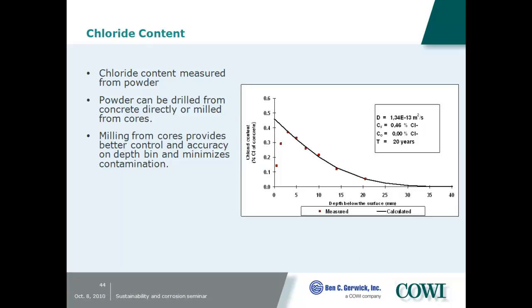Chloride concentration, either from powder or from ground samples from your concrete core. We can measure the average diffusion coefficients over time, and they would be different from those you measure at 28 days for durability design. You can measure them after a longer period of time, and you can estimate how long it will then take before you have a possible issue with chloride-induced corrosion at your reinforcement depth.